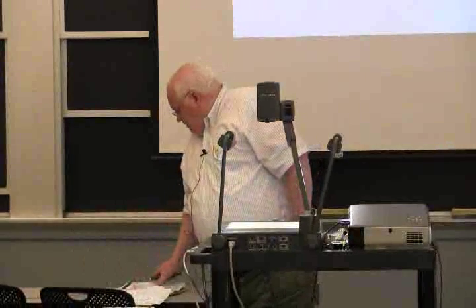If you get rid of the oxygen before you pour it, it's called a killed steel. This is a semi-killed steel. These are unkilled steels, or we call rimmed steels, and these have carbon boils. These are for sheet material. This is for plate material. Does that answer your question? So those are things we had to worry about. In the old days, rim steel gave excellent surface quality, whereas with plate steels, you end up with inclusions and other things on the surface.